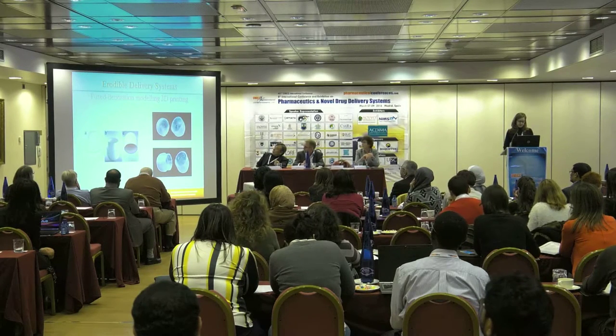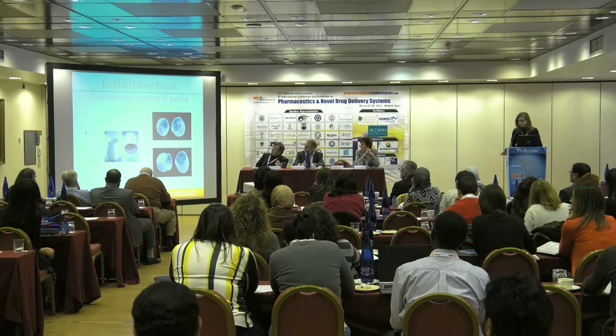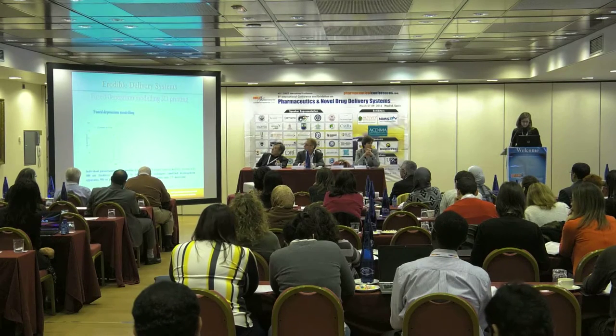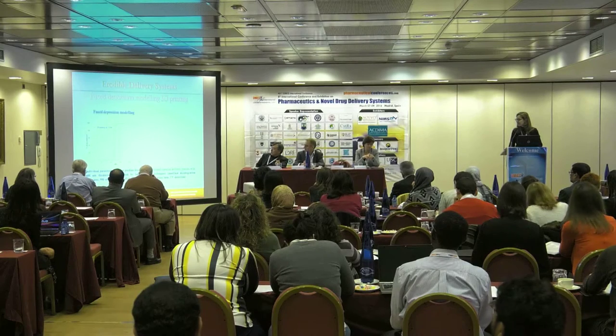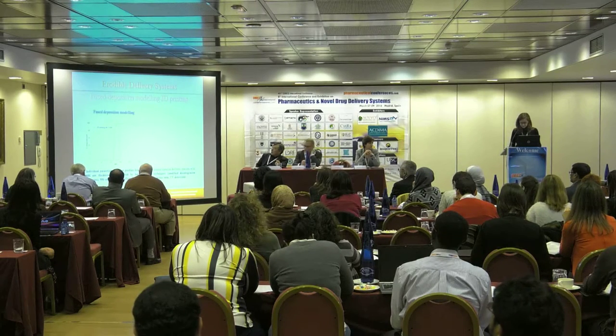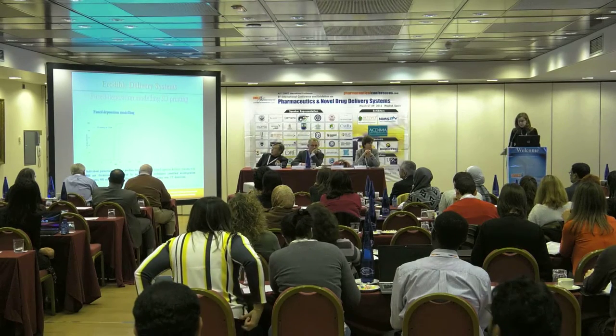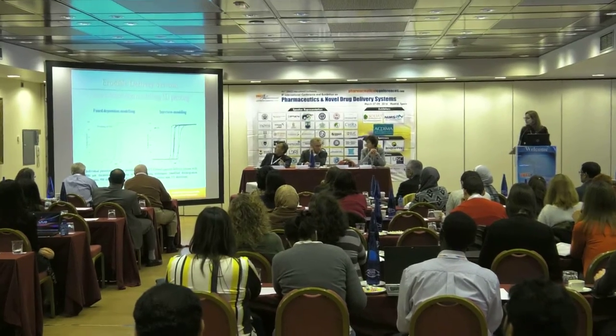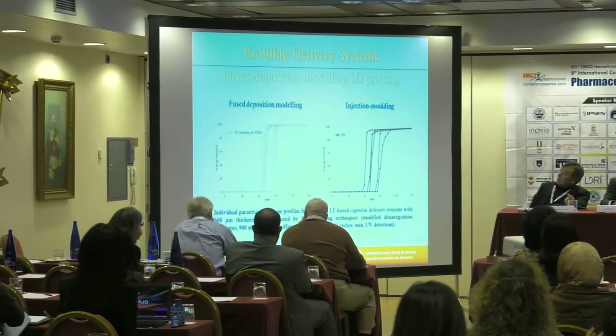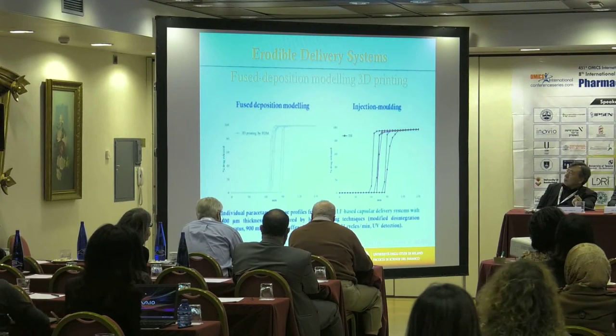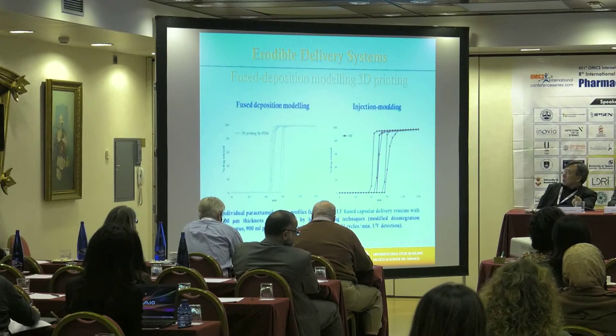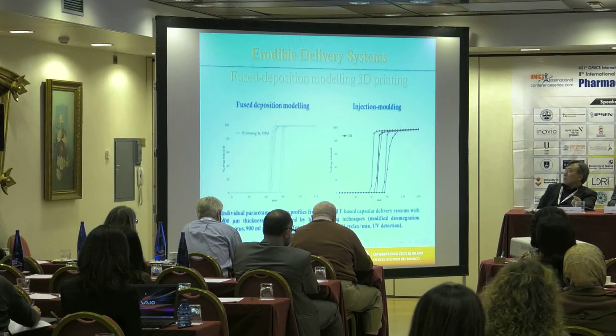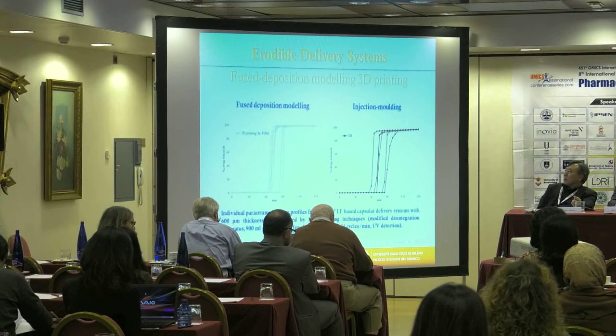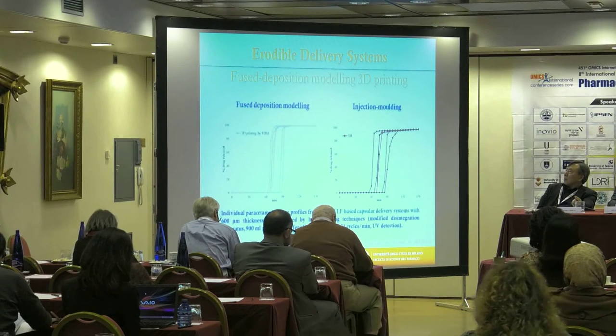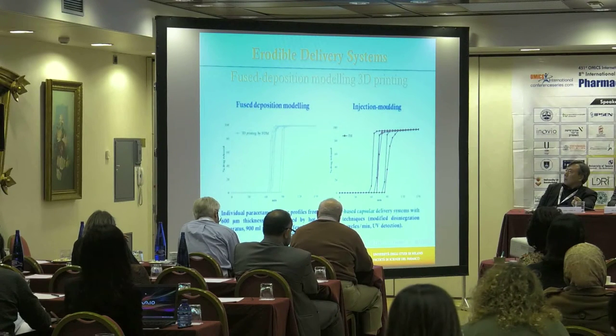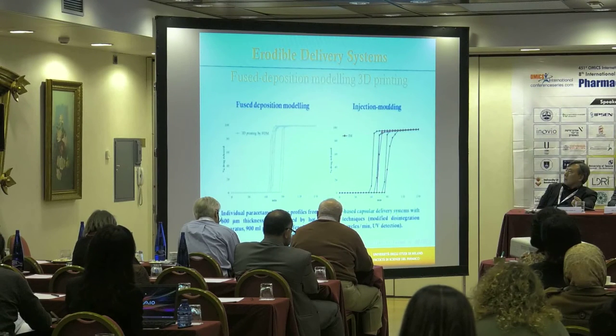Finally, caps and bodies of capsule shells having acceptable physico-technological properties were manufactured and assembled into a drug-containing device. They provided the typical lag phase followed by a rapid release at the end. The in vitro performance of the printed capsules was fully or largely corresponding to that previously exhibited by molded capsules, and this result, though preliminary, would support at least the real-time prototyping potential of fused deposition modeling versus injection molding in the manufacturing of erodible delivery systems in the form of capsules for time-controlled release.